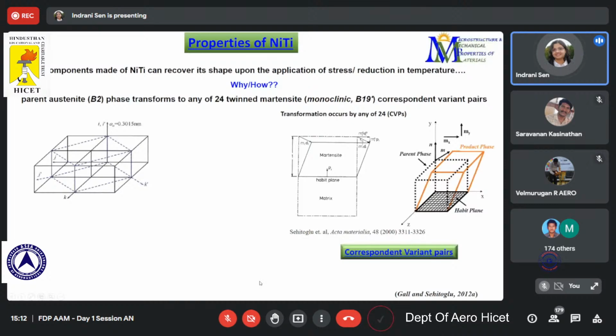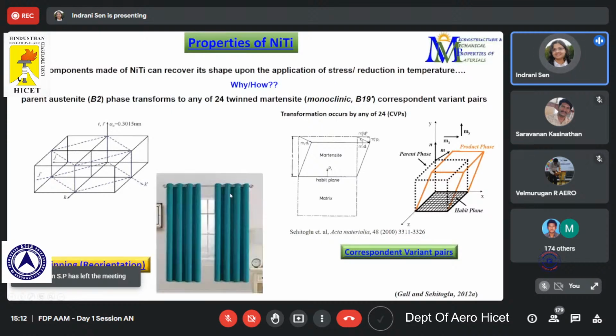Then once this conversion from austenite to martensite is done, if we apply stress, there is detwinning happening. Initially martensites are formed as twins, and if we apply stress, it gets stretched up like this. I have shown this with the Venetian blind curtains, so you can understand that if we try to stretch it, it gets stretched. Similarly for the martensite twins also, if we apply stress, it detwins, which is also known as reorientation.